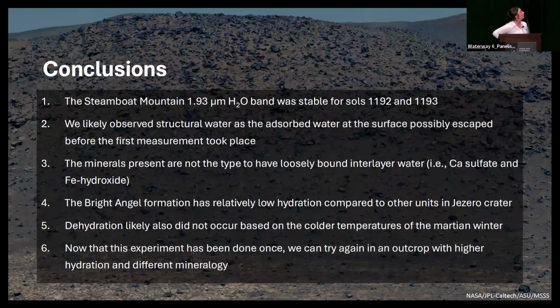So to conclude, at Steamboat Mountain, the 1.93 band appeared to be relatively stable because we didn't see any significant changes. Again, we're looking for changes greater than 2% because that's what we go for in the lab, and that's also above the instrument noise level. We likely observed structural water and not adsorbed water. In the laboratory, we can see adsorbed water begin to liberate from the samples after 10 minutes. But we didn't see any changes to the long wavelength wing of the 1.9 band that would be indicative of that.